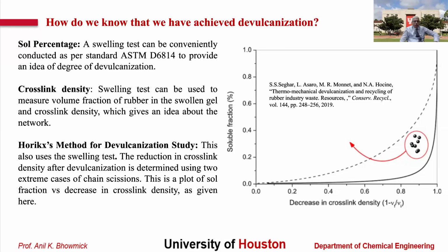And if you want to specifically know what is the percentage of sulfur-sulfur bond breakage versus main chain scission, you can do a Horikx method for devulcanization study, which plots sol fraction against the decrease in crosslink density, which is shown on the right-hand side of this slide. And you can see that if the points are close to the solid line, that means more sulfur-sulfur crosslink breakage. Next slide, please. Next slide.